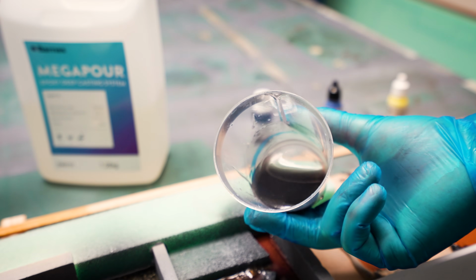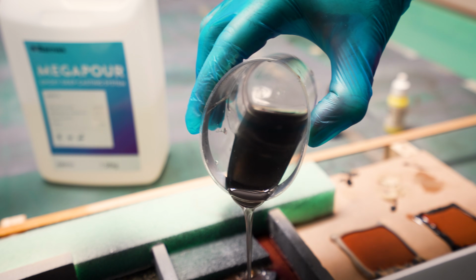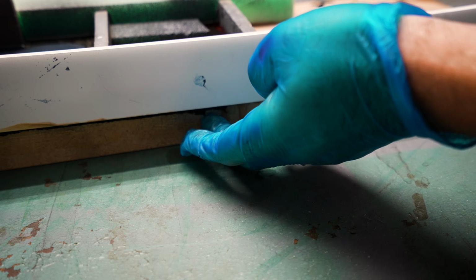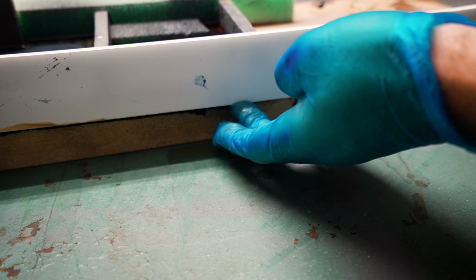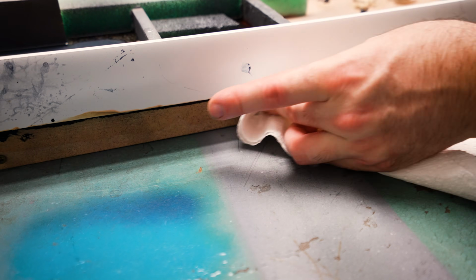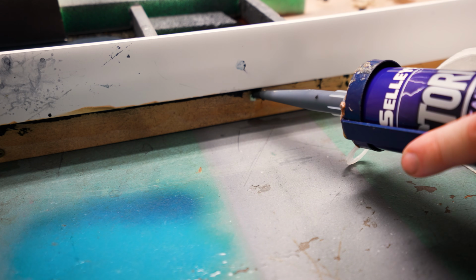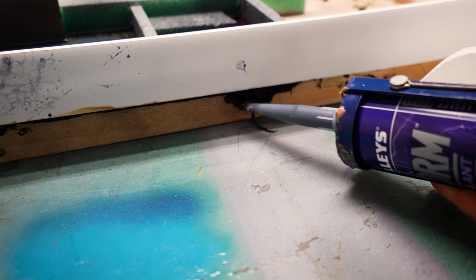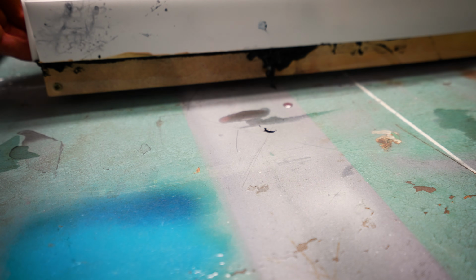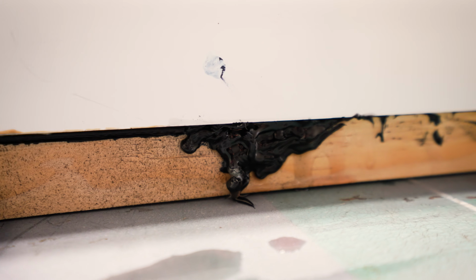It was at this point I realized I definitely had a leak in the gate for the red-brown compartment, which might seem small, but it's pretty much fatal if left unattended because of how long this resin stays runny for. A perfect test though for our storm sealant. I slapped that all over the place, and it was a complete failure. That is not going to stop resin from leaking.